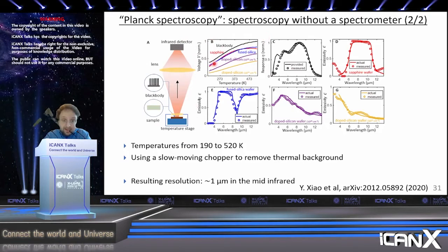So this is for the black body. This is for a piece of sapphire, a piece of fused silica, and a couple of samples of doped silicon with different doping densities, essentially just different samples with different emissivities. You can see that each one of these curves is quite different in terms of its spectral shape. It's not too different, so you can imagine that going backwards to figure out the emissivity spectrum is not easy, but they are different, and so it is possible. Of course, the black body has the highest emissivity, and so it's on top. In this case, the doped silicon at high densities is the closest to being metallic across the whole wavelength range, and so it has the lowest emissivity over here. So here are the experimental results.